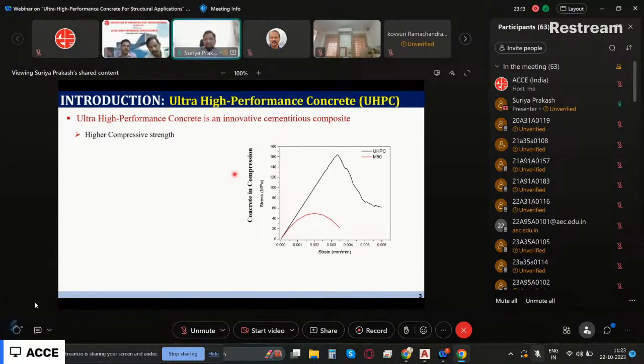Now let us look at this. I'm taking M50 concrete. If you test a concrete cylinder in the lab and you get this kind of a stress strain curve, that is what we use to design structural elements. Because to design, I need to know how the material is behaving in compression, tension, and so on, right? So this is a material, the black color is the one with UHPC that we have developed. In fact, anybody can develop it. It's not a big thing, but you have to do a lot of trials and then you have to come up with a proper procedure to develop that mix design.